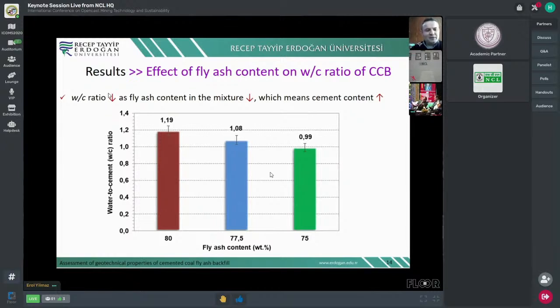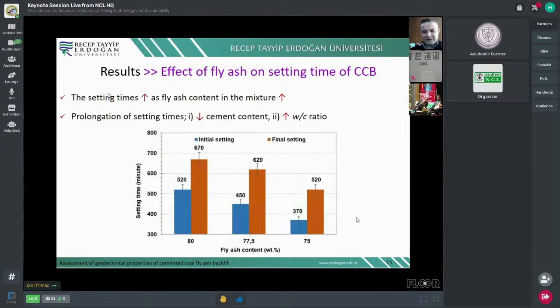You can see the water to cement ratio decreases as the fly ash content in the mixture decreases, which means the cement content increases. So when you increase the cement, the water to cement ratio is getting down a little bit. You can see the green bar.